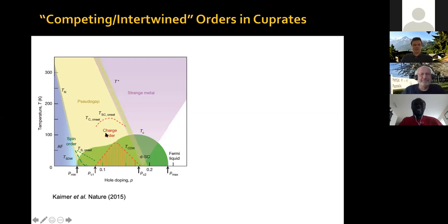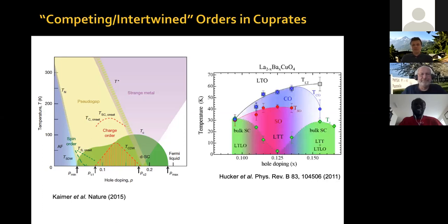You can see that in this phase diagram there are different phases, and in particular there are some phases which seem to be intertwined with each other, meaning some orders which are present, and in some cases they seem to compete like this. The presence of this dip in TC, rather than just a dome that you would have expected continuing like this, has been attributed to the presence of charge order in cuprates. For some cuprates, like lanthanum barium copper oxide, this depression of TC can be almost all the way to 0 at this 1/8 doping.